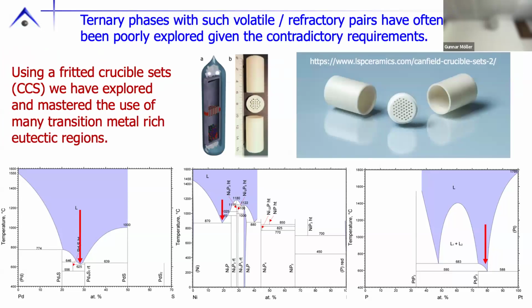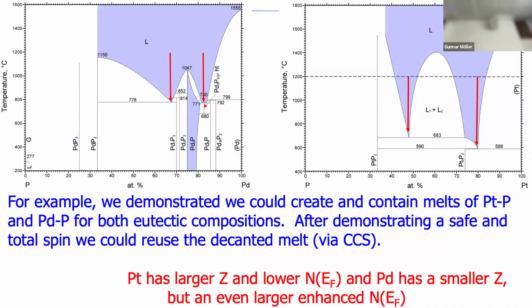So in that case, what we've been doing is first making sure we own the eutectic. And we do that by putting our elements into the base of one of these fritted crucibles, heating it up, making sure nothing explodes, cooling it down, spinning right above the eutectic temperature, making sure the phase diagram is correct. And if we can do that without any evaporation, without any evidence of high pressure, without any bad things, we consider ourselves owning this eutectic, owning this region, and we can then try to do growth. Okay, so let me show you some examples.